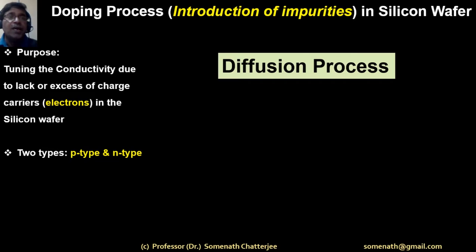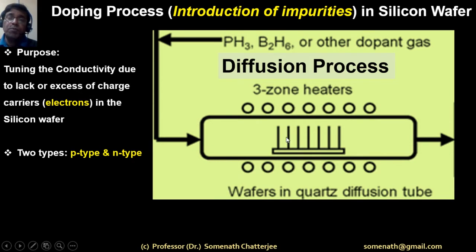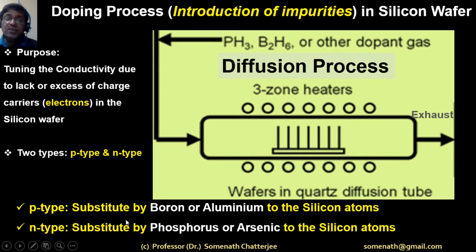The process is doping, which uses diffusion or ion implantation. In the diffusion process, there is a thermal processing chamber where we can place the wafer vertically. The source of the precursor — we are using phosphine or diborane — comes in as a source of the different element. By the diffusion process or by the ion implantation process, the silicon atoms will be substituted by trivalent elements like aluminum or boron, or pentavalent elements like phosphorus or arsenic.